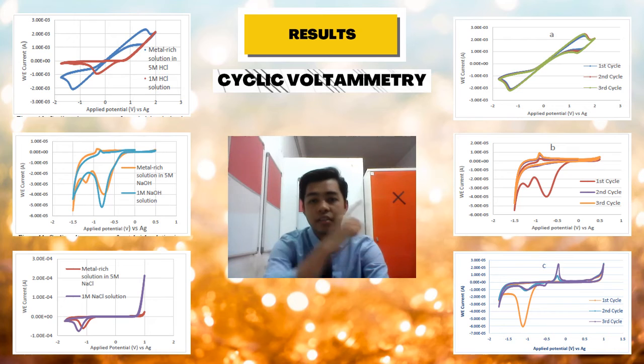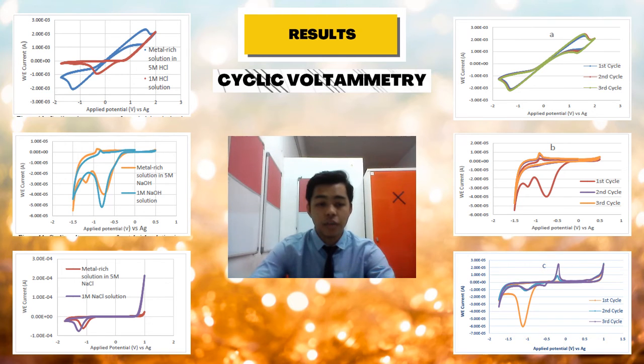Moving on to the right side graphs. These three graphs indicate the metal-rich solution reaction in 5 molar hydrochloric acid, sodium hydroxide, and sodium chloride without comparing with the background. We take the first graph, which is the graph for the metal-rich solution in 5 molar hydrochloric acid. This graph compares the reaction happening over three cycles. We can see it shows an electrochemically reversible system as there are 3 peaks formed at cathodic and anodic current.